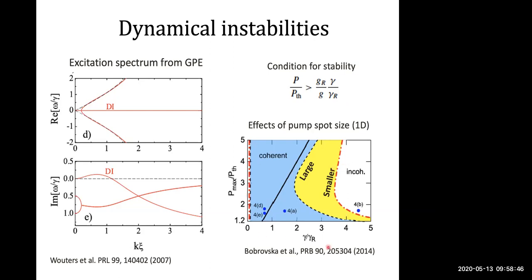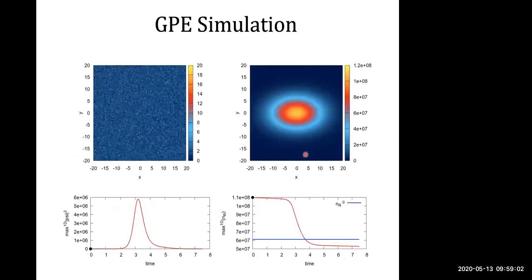Numerical simulations have also shown that the size of the pump spot plays an important role in determining whether this instability will exist or not. For large pump spots, the region of stable condensate formation becomes reduced. And we were able to study this numerically. I'll show these two simulations and then I'll wrap up. If you excite one of these systems, and these are all parameters known from experiments, with a small pump spot, then you stay in the stable regime.